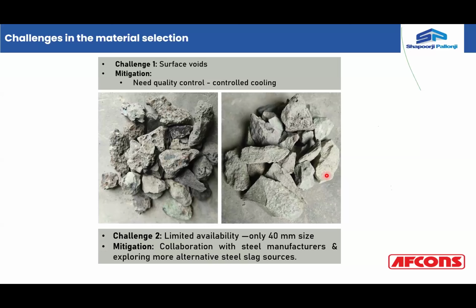So, in short, the only challenge we have faced in steel slag in particular is that there are particles which have surface voids, as shown on the left hand side. The intermixing of these types of aggregates will deteriorate the properties of the steel slag, because these are soft and these are being created because of the lack of proper cooling operations. So there needs to be perfect quality control, which will always give you aggregates having a less porous surface, as shown on the right hand side.